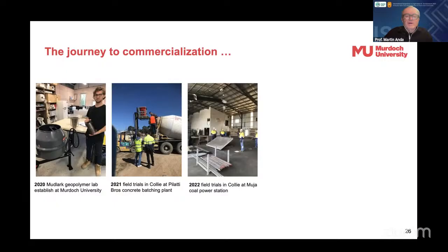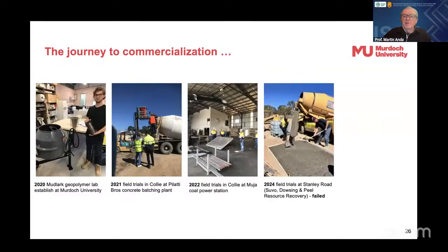And then we actually went into the Muja coal-fired power station in Collie, probably the biggest coal-fired power station that we have in Western Australia, and in one of the empty warehouses we actually started manufacturing wall panels with geopolymer that we made at the batching plant, and that actually was able to work effectively. We did have an unsuccessful field trial later in 2024, trying to get ready mix to work. That was also quite difficult,